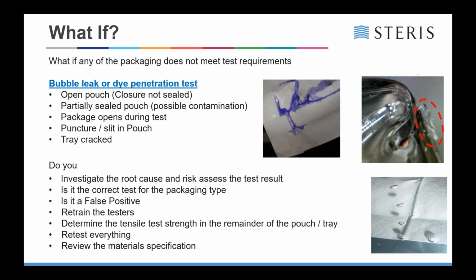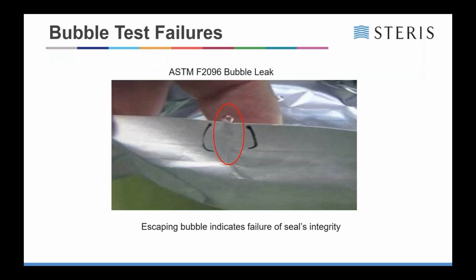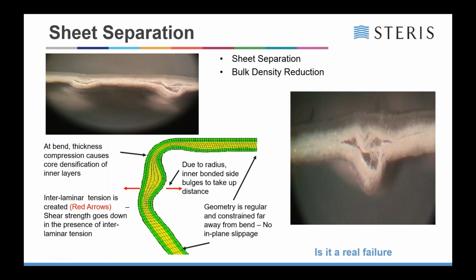If you're getting punctures, if you're getting trays cracked, which is very common, depending on whether they're from the final molding or from an engineering mold, again, you see lots of different types of defects coming through from the various manufacturing processes. As I mentioned, the escaping bubbles from the seal can be caused where the material has been folded over, so you're getting sheet separation or sheet bulk density reduction.